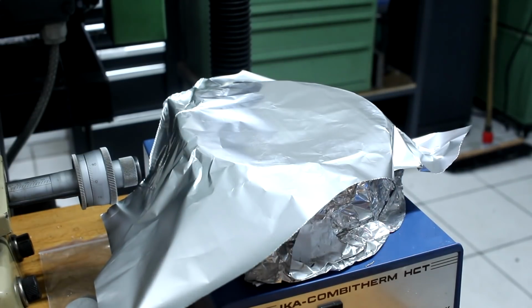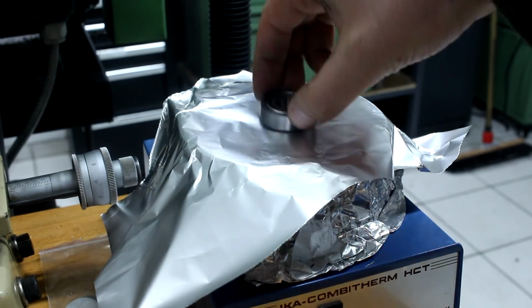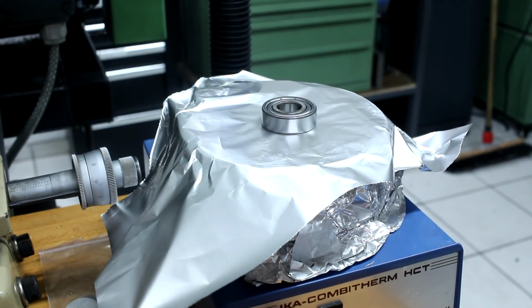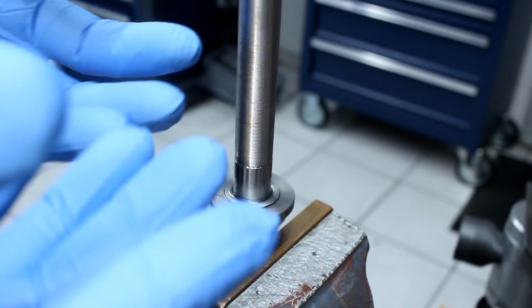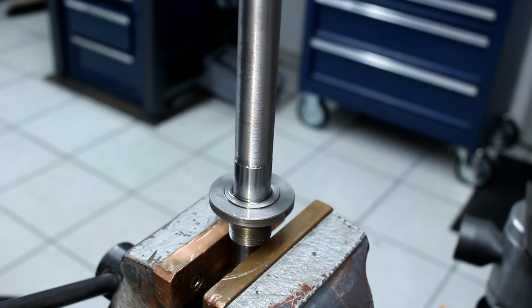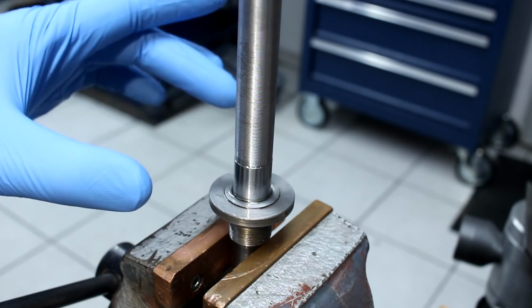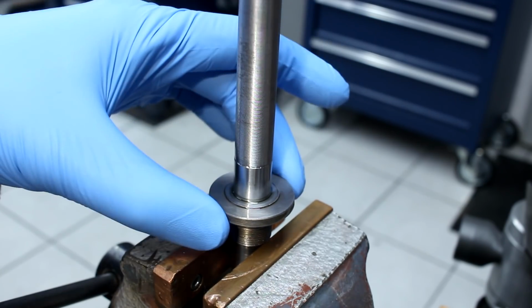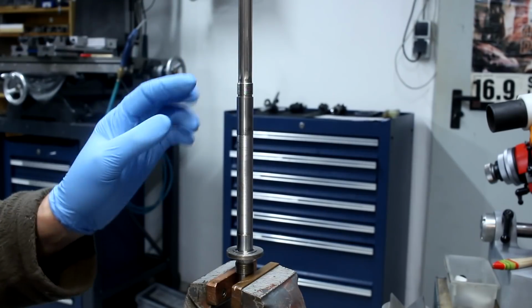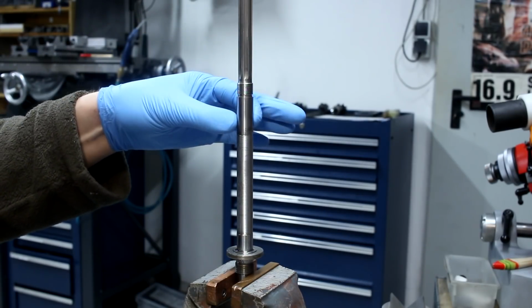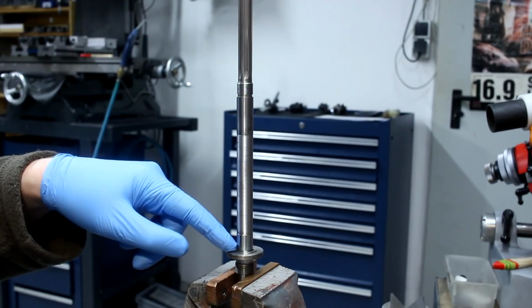Fresh piece of aluminum foil, a clean bearing. So I put this on at about 120 degrees C. 100 degrees C is what most bearing manufacturers recommend as a maximum when you do a shrink fit with a bearing. Okay, bearing is hot. I had it soak for about 7 or 8 minutes at a little bit over 100 degrees C. And I have the spindle in the vice, vertical. I have to pass 2 bearing seats. First the thread, bearing seat, and then I want the bearing to go on here.